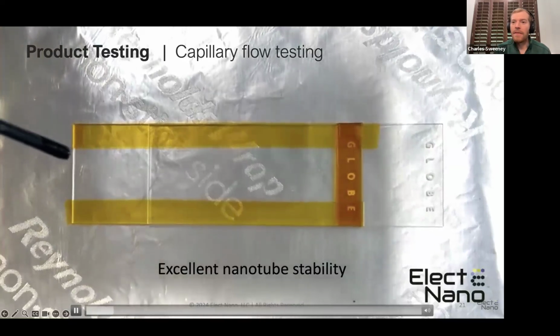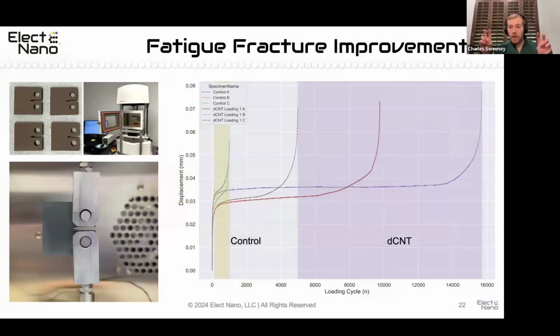And so after you do things, quote unquote, the right way, when we were testing K1C and the fatigue fracture performance of these materials, we were happy to discover that compared to control specimens, same formulation, just with silica filler and without nanotubes, they typically fail under 1,000 cycles. And with carbon nanotubes added into these systems, we're basically hitting over 5,000 up to 15,000 cycles before the fatigue crack propagates through the material.